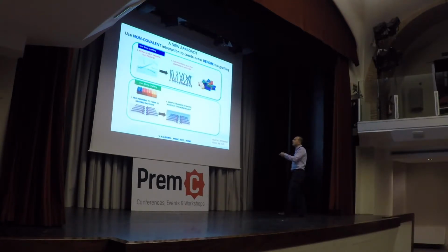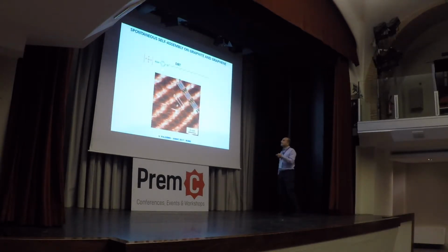Then we move them to a solvent, which is water, that fixes this morphology, so they cannot move anymore. And then we apply the electrochemical pulse, and this transforms the physisorption into a chemisorption. So it's a two-step process. You first position the things where you want, then you trigger your reactivity. That is the idea. That's why we use these molecules with a very long alkyl chain, because the alkyl chains force the molecules to form these very nice arrays.